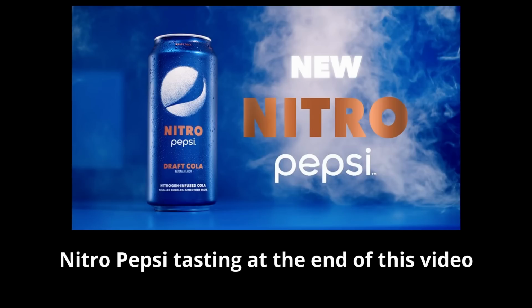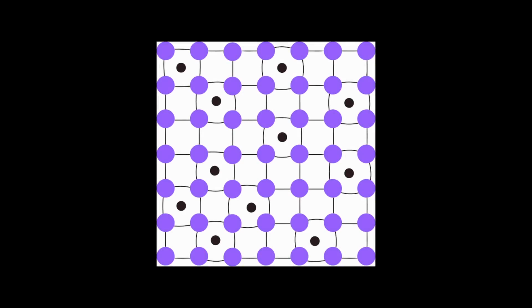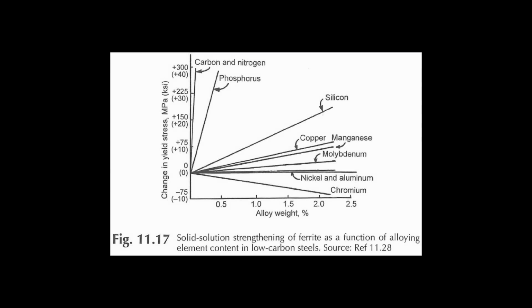So, yeah, nitrogen acts similarly to carbon. You know, just like they replaced the carbon dioxide in the Pepsi with nitrogen, we're replacing carbon with nitrogen in the steel, either partially or entirely, depending on what steel we're looking at. So those little nitrogen atoms go in between the iron atoms, which is the same thing carbon does. But when you quench it from high temperature and form your hard phase martensite, those little interstitial atoms increase the strength and hardness of the steel. So yeah, carbon and nitrogen work the same way.